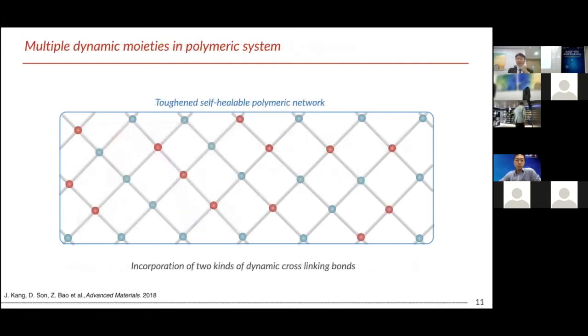My approach is quite simple. I imagined that if we can incorporate two kinds of bonds with different bond strengths, the two bonds may play roles independently. One is a very strong bond to impart elasticity, and the other is a weak bond that shows very fast energy dissipation to promote the self-healing properties.